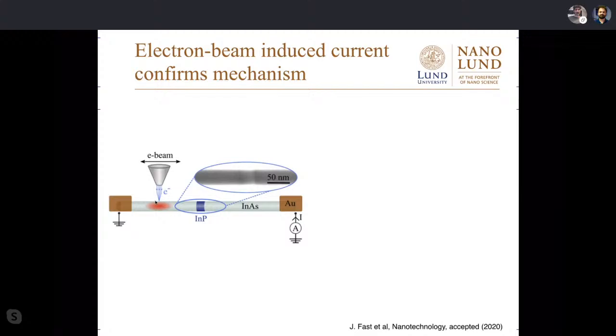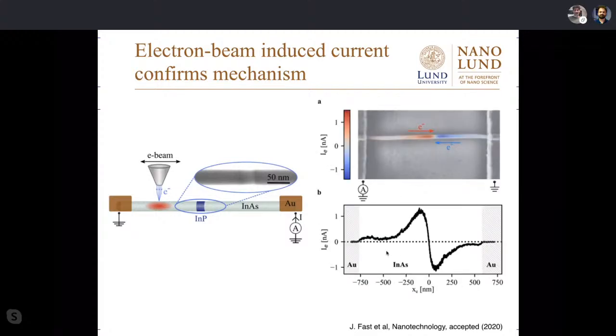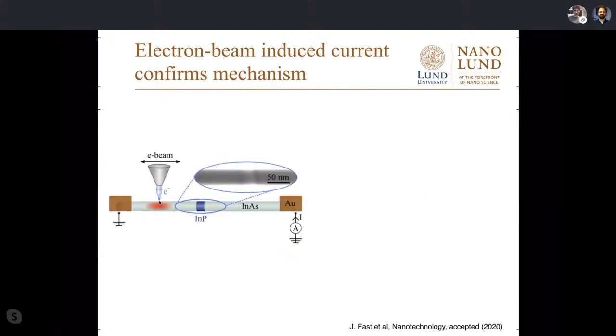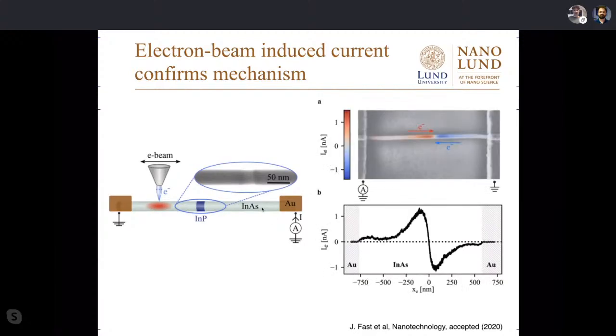So we create electron hole pairs somewhere and check what current we get out, as a function of position. So you scan the electron beam along here and then check how much current I get. It shows very nicely what happens at the barrier. If you put electron hole pairs close to the barrier, you get current in one direction. If you put them on the other side of the barrier, you get current in the other direction. So this is consistent with electrons jumping over the barrier, just what we had in mind.